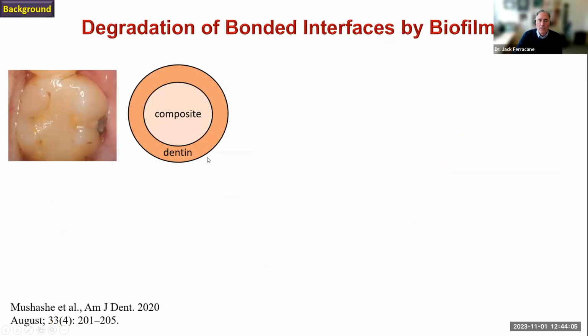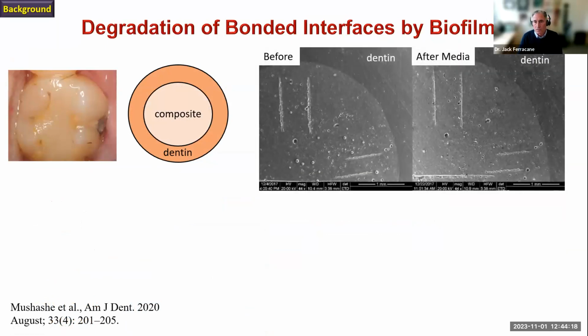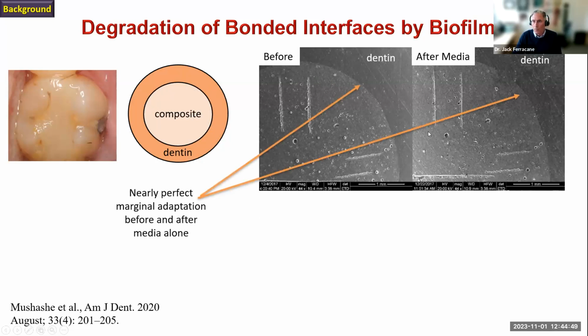What we found out more recently is the fact that even when we have a good bonded situation, we may have degradation of this bond over time and opening of gaps because of the effect of biofilms on composite restorations. Composites are good surfaces for biofilms to form. And so this is a little experiment that was done by Dr. Mushashe for her PhD, in which a composite was placed inside of a dentin cavity. And what you're seeing here is the replica of the surface. And you can see this is the nice tight margin, in both cases, before and after exposure of the restoration to just media alone, bacterial media alone. And the margin holds up very well.